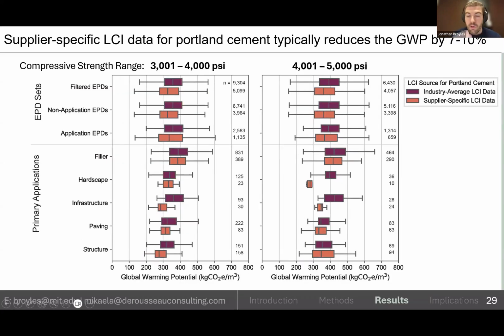And then lastly, we wanted to compare the concrete mixture GWPs based on the type of LCI data that they reported for Portland cement. So this is not Portland limestone cement, this is just Portland cement. And we were just comparing those EPDs that reported either supplier-specific LCI data, or used industry average LCI data. And you can see, again, these results are pretty consistent, but we found that roughly using supplier-specific LCI data reduced the GWP by about 7 to 10% here.